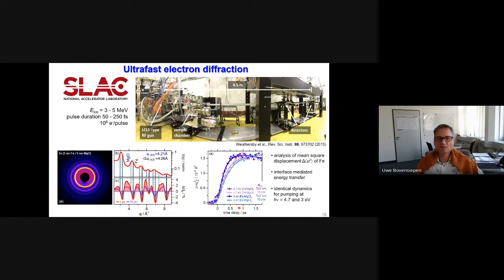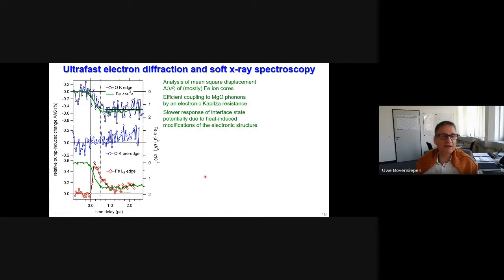So this means we really have this electron-phonon coupling through the MgO interface, what I mentioned earlier to describe the X-ray data. We compare also to bulk structures of 10 nanometer. These are these slower responding traces, which really means that we probe the energy transfer across the interface. And we can now plot this change of the mean square displacement right on top of our X-ray data.